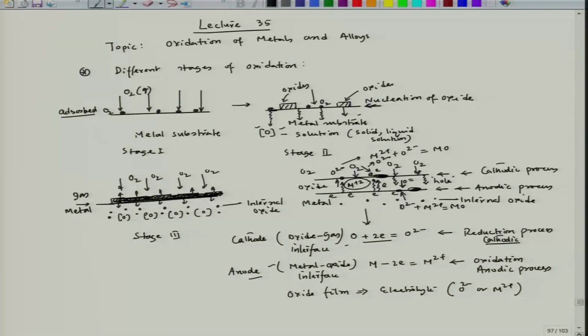That means, we know that an electrolyte holds ions and also helps in migration of ions. So, oxide is acting as an electrolyte. Now, this electrolyte also flows charges, the charges in the form of electrons or positive holes. Those charges can also migrate through that electrolyte. So, this is also acting as a conductor, since electrons or holes are migrating or moving.